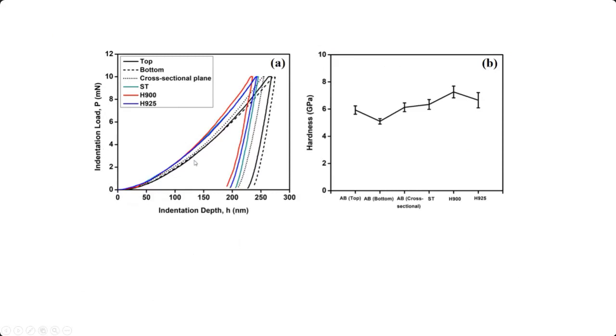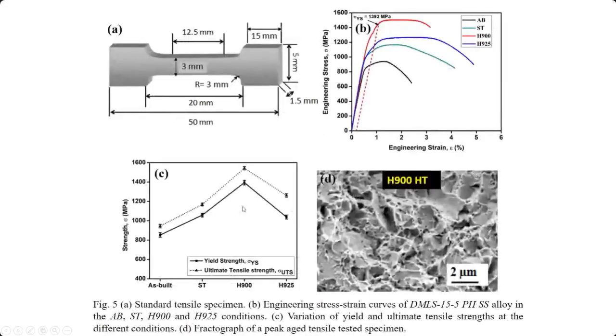This is the indentation studies that has been done, nano indentation studies, for the top, bottom, cross-sectional plane, as well as solutionized and aged at 2 different conditions. We will see how the hardness varies, and we get the best result if we are heat treating it at a particular temperature and time combination of the additively manufactured sample.